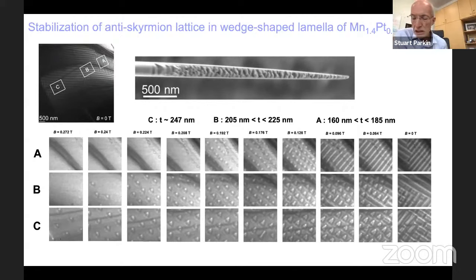And it turns out in this Heusler material, the orientation of this helical structure is set by the crystal lattice. So I don't know if you can see, but in this image shown on the top left, you can see a region A where the black and white lines are approximately perpendicular to the foil, and in region B, they're parallel. And this is because these are two crystallographic directions which favor the block type of walls. And these two directions have the lowest energy for these helical structures because these block-like walls have less energy.